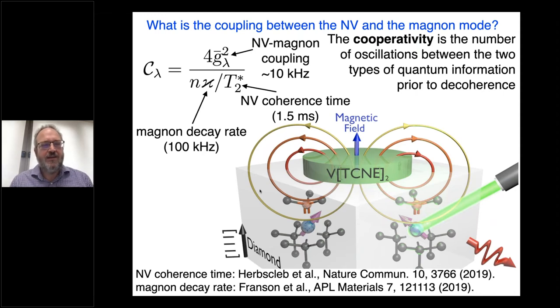These parameters, particularly that NV-magnon coupling strength, depend on the size of the disk. And the relevant size of the disk really is of order a micron, because the idea that we're working with is that it's very difficult to address multiple spins together. If you look at the characteristic length scale for the exchange between two spins, it's of order nanometers. Exchange or dipolar interaction, maybe a few more nanometers, but still very small distances. And so we really want to make these solid state qubits bigger. It's a bit counterintuitive, but how do you make them bigger? In part, the way you can make them bigger is by having